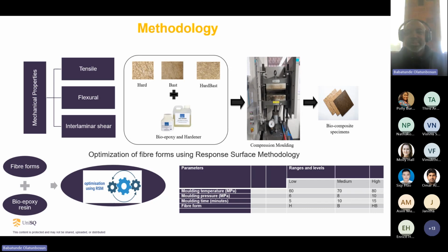to produce bio-composites. I use what we call response surface methodology to optimize the fiber form and the bio-epoxy resin. And these are the mechanical properties, the responses, I'm looking at: tensile, flexural, and interlaminar. The tensile and flexural have to do with the fiber, while the interlaminar has a great influence from the bio-resin. The table below shows the parameters and the ranges or levels I use. The manufacturing parameters are molding temperature, molding pressure, molding time, and the fiber form.